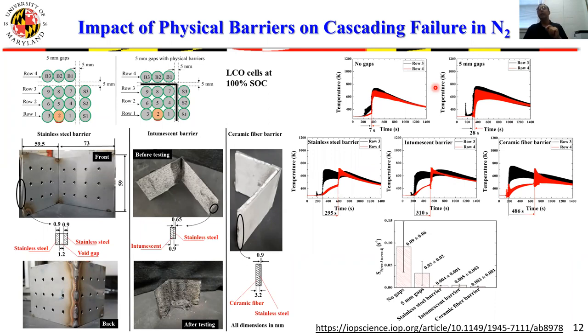We did find that adding physical barriers, which usually required a sturdy structure like a stainless steel sheet combined with some sort of thermal insulation, and we tried different ones, that structure, when introduced into this gap, actually slows down the thermal runaway progression or cascading failure considerably. With a ceramic fiber barrier combined with stainless steel, we were able to achieve a delay of the thermal runaway of about 4 minutes or so, which is now considerable. So with the introduction of barriers right there into the structure of the modules, you can actually reduce the severity of the battery fire and give potential occupants, if it's near human occupancy, time to egress before this fire becomes severe.